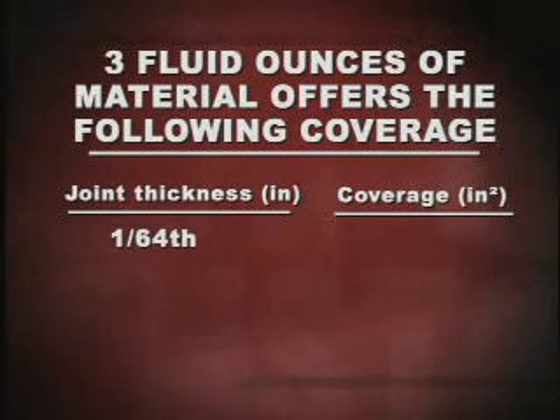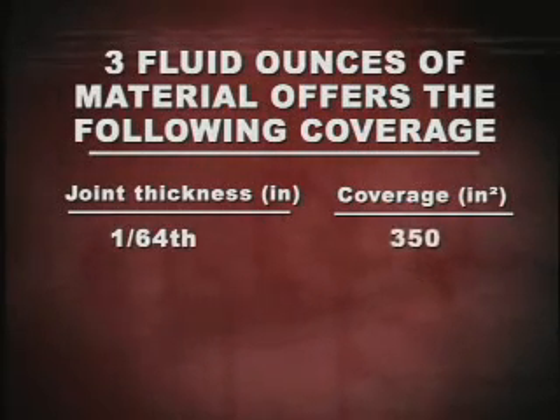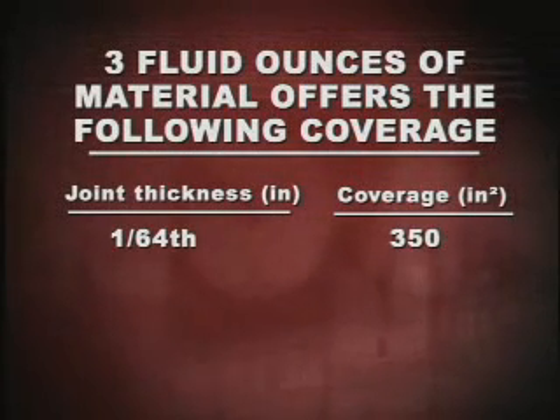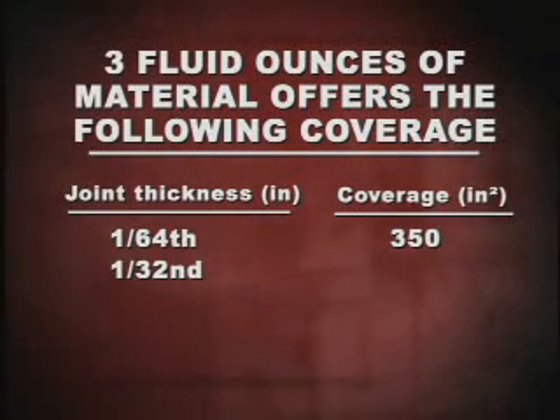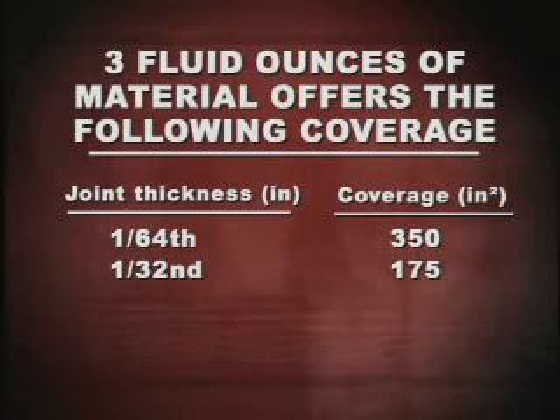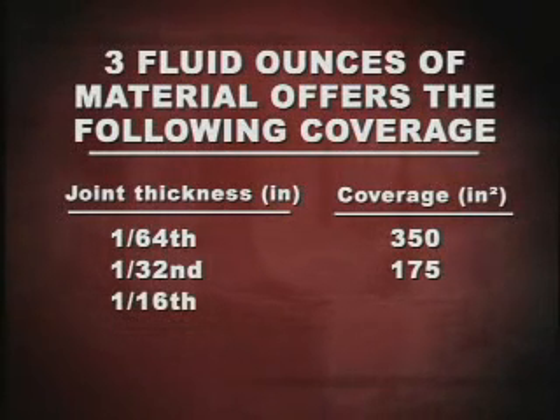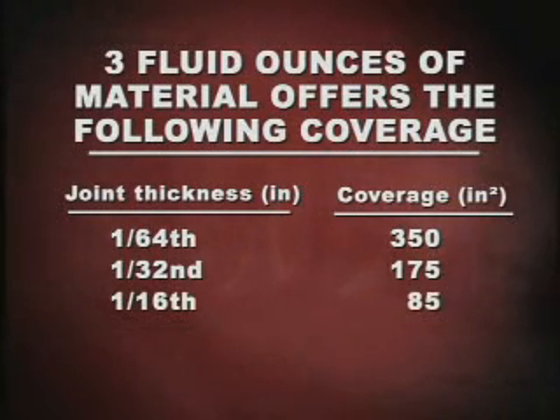If your joint thickness is 1/64 of an inch, you can get 350 square inches of coverage. At 1/32 of an inch, your coverage is about 175 square inches. And at 1/16, it's 85 square inches.